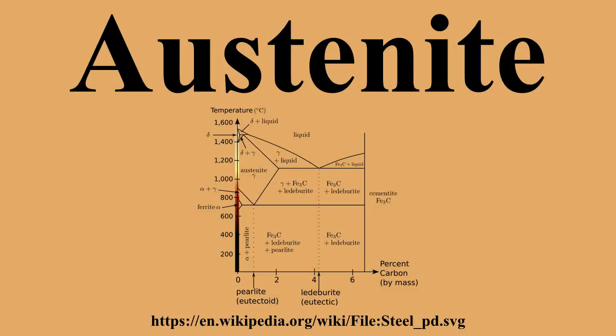With the transition from a deep cherry red to orange red to 871 degrees Celsius, corresponding to the formation of austenite in medium and high carbon steel. In the visible spectrum, this glow increases in brightness as temperature increases, and when cherry red, the glow is near its lowest intensity and may not be visible in ambient light. Therefore, blacksmiths usually austenize steel in low light conditions to help accurately judge the color of the glow.